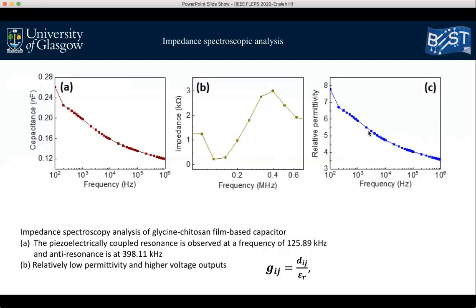And then from the analysis, we observed that the relative permittivity of this material decreases with increasing frequency, and the relative permittivity or dielectric constant is quite low. This low permittivity suggests that this beta-glycine chitosan composite is a good candidate for a high performance sensor, and the reason is that the piezoelectric voltage coefficient, which is g in this formula, which is defined by the output voltage under applied stress, is a crucial parameter to obtain a film with high performance in terms of producing high voltage.